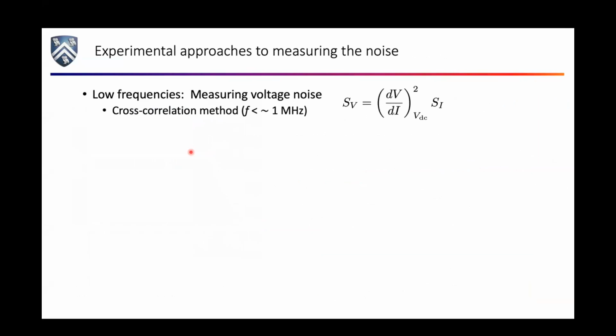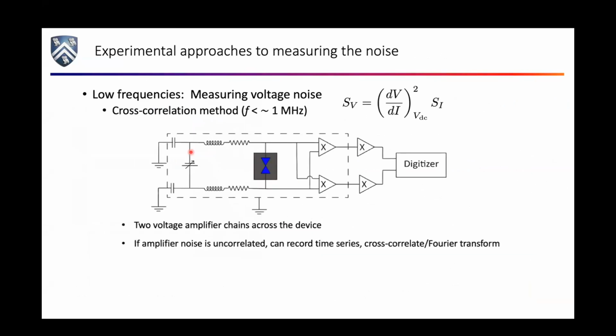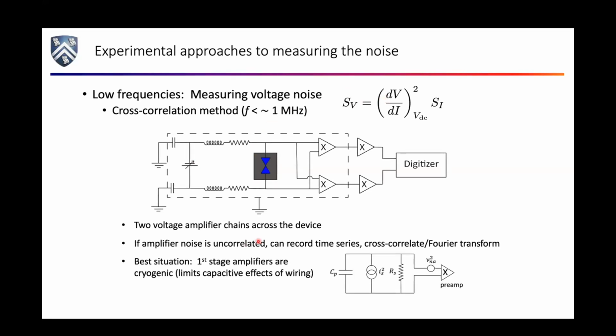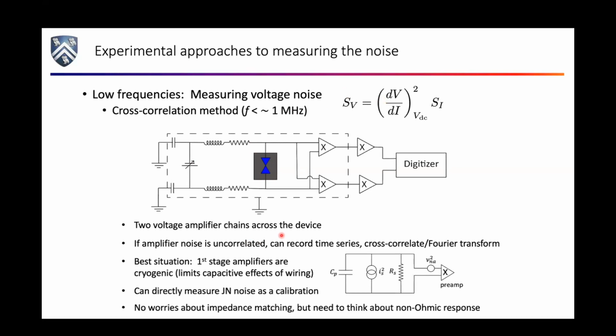This has been measured before in ordinary metals, and we do it too, just to make sure we know what we're doing. So what you do experimentally is, here's your device, and you just look at the voltage across the device and digitize this as a function of time. In fact, we do this with 2 independent amplifier chains so that you can null away the amplifier noise. And you just digitize it, Fourier transform it, and cross-correlate it, and you can get the voltage fluctuations. And knowing the differential resistance, you can turn that into current fluctuations. Okay. So if you do this, you can make some nice progress.